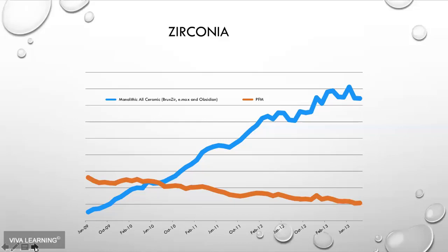These are the number of units generated from Glidewell Lab, which is a great sample size, being that they're one of the largest, if not the largest lab in the country. This shows from 2009 to 2013 a significant decrease in PFM, a significant increase in zirconia and lithium disilicate. And that trend has most certainly continued to the point that a few years ago, Glidewell no longer makes PFM crowns because the demand just is no longer there.